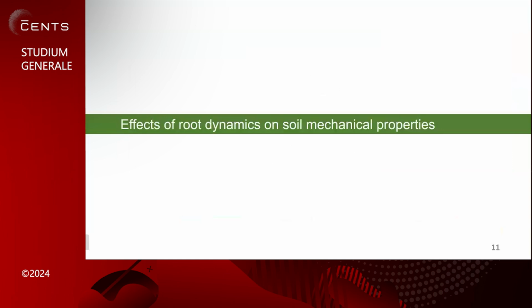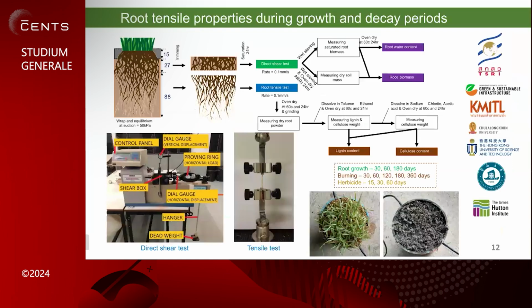We are studying in the lab. We plant the grass in a column, and then we divide it into two parts. The first part we use for the direct shear test, and the bottom part we use for the tensile test. For the direct shear test, as you can see in the figure here, we put the soil in and then do the shearing. In this case, we can see how much the shear strength can be improved with the existence of the root. We also do the tensile test to pull out the root, so that we can see how much tension the root can resist.